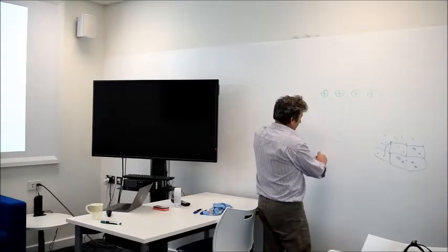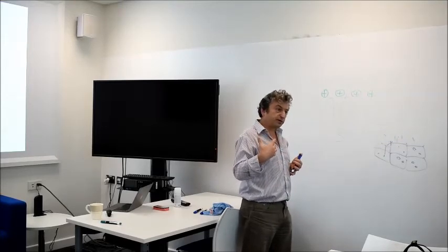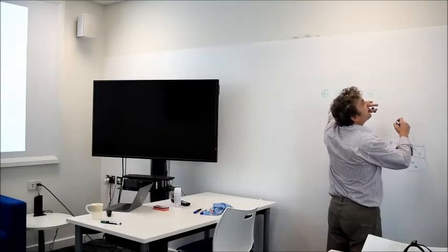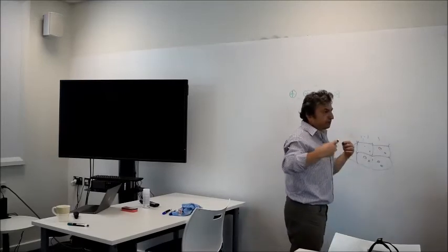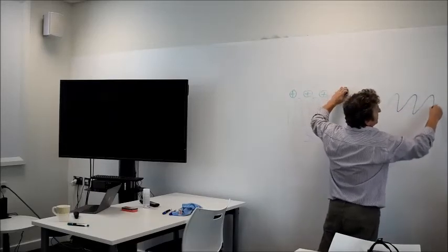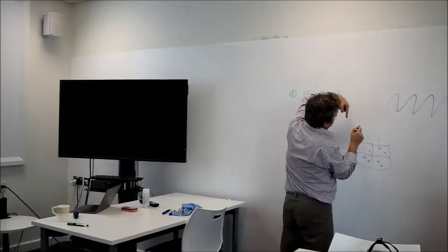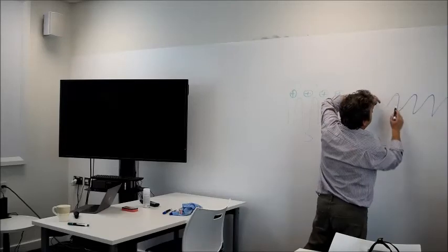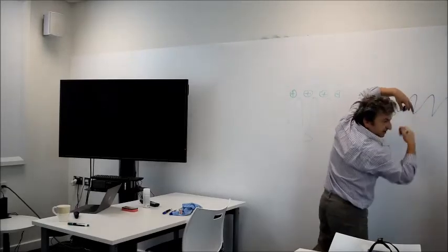When they did it with a constant current, because it's easier to do manipulation with constant current rather than constant height, as I showed before, they record what the tip does, going up and down, up and down. So they have images going like this. Each time the C60 is moved, the tip behind it remains there, and the C60 moves, and the tip goes down because there's no matter underneath. So it goes up when the C60 moves, then the C60 jumps to the next position, the tip is not that fast, so it goes down until it comes again to the C60, climbs, then C60 is moved, yeah?